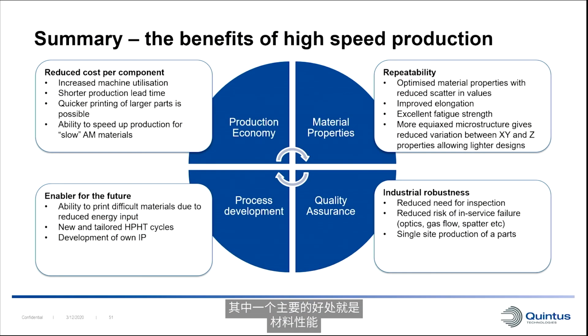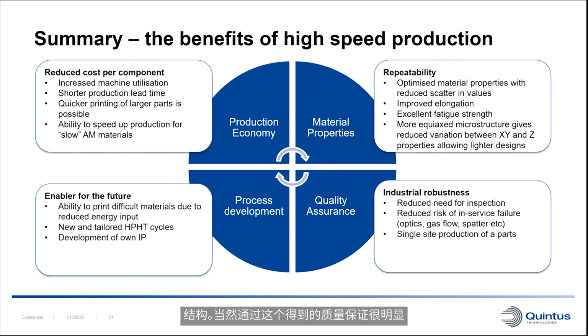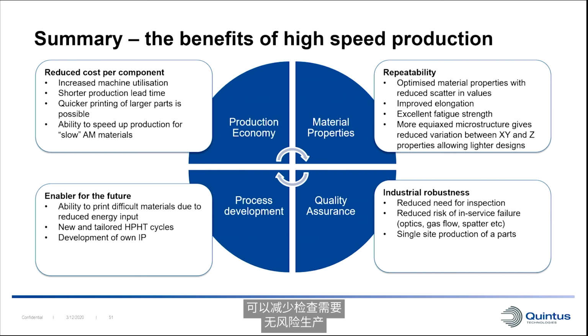One of the major benefits is really the material properties, the repeatability of this, where you can see that the spread in the results can be reduced. We can get optimized material properties the same every time, with improved elongation, excellent fatigue strength, and of course more equiax microstructures based on the HIP process itself. The quality assurance aspects that come from this are, of course, clear. And industrial robustness is a key area here, where the reduced need for inspection, the risk-free production environment, and also single-site production of parts, where by not sending parts out for subcontract processes is a major opportunity.